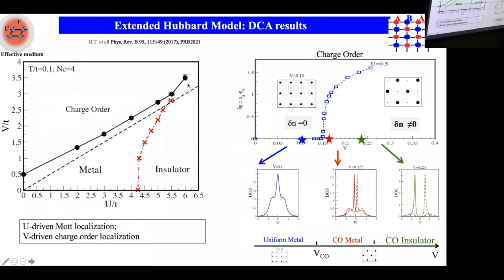Yeah, that's interesting for high temperature superconductors because at high temperature it looks like it's going to be insulating, and then you get charge order, and then you get quantum oscillations. So that's sort of what's expected, but it's nice to see it in a calculation. We need to tackle better the way to reduce the sign problem introduced by V. Yes, in this regime, which is interesting.